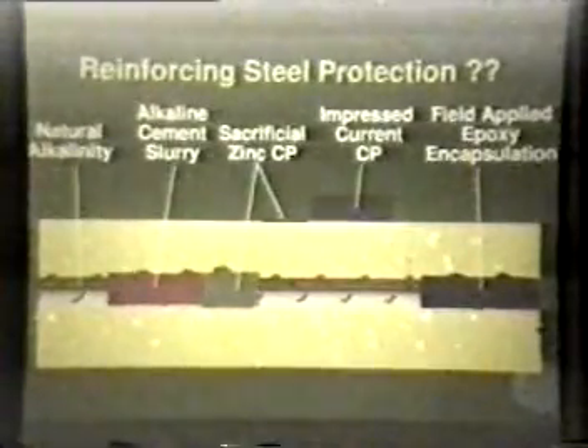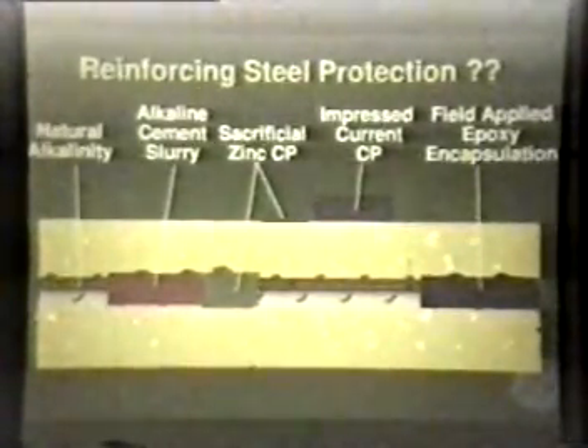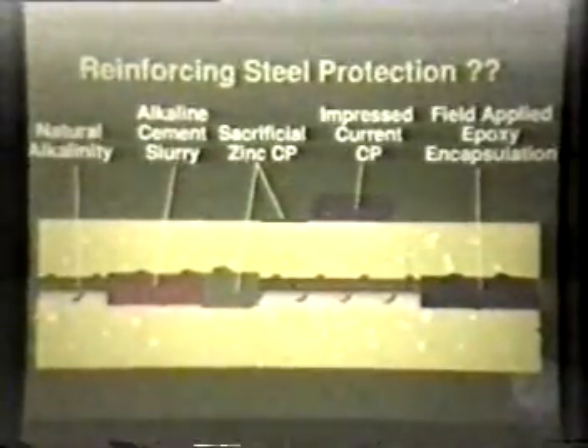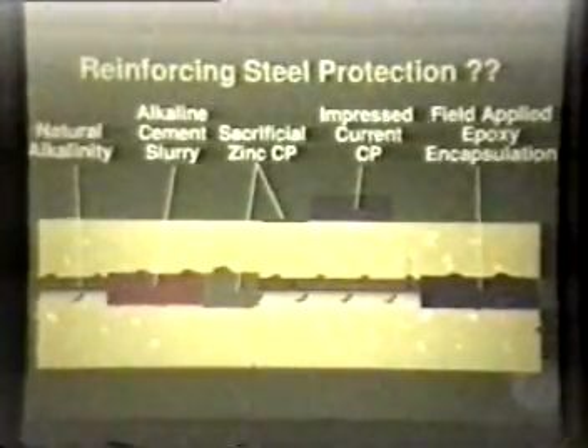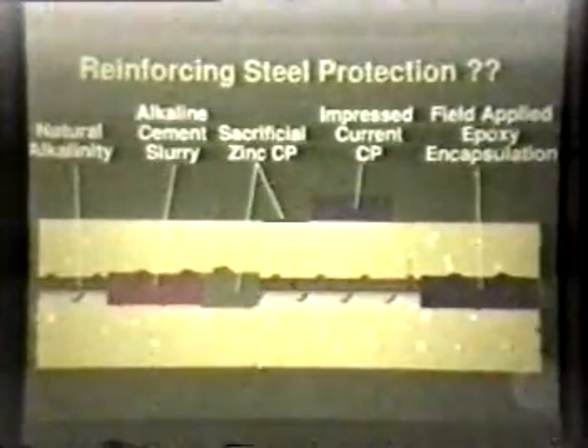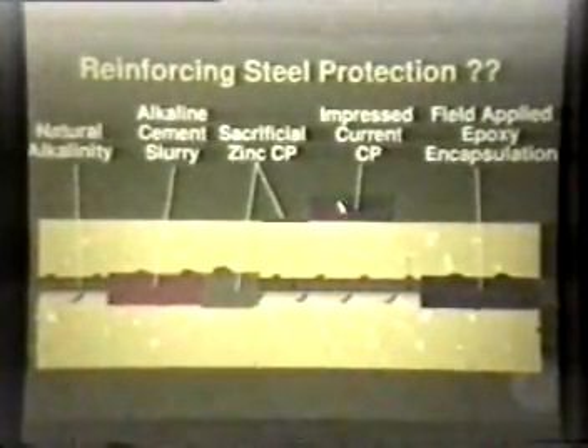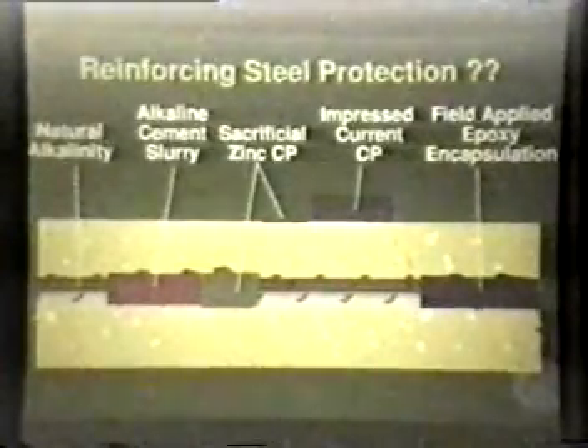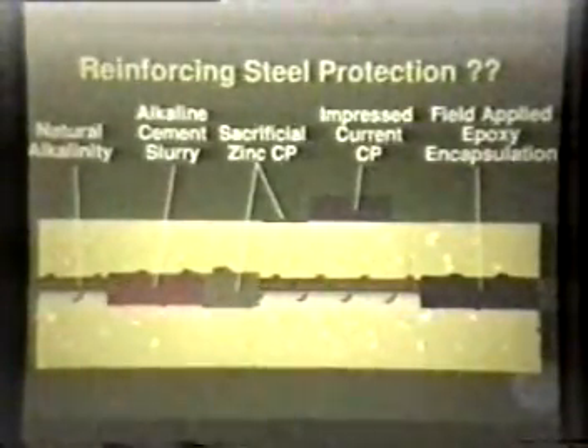In general, what I see is the epoxy coating systems have fallen out of vogue for repair and have led to different specialty coating systems that are based upon either the alkalinity protection. The alkalinity of concrete is a natural protection. It has a high pH, and that high pH is what protects the concrete. It causes passivation of the reinforcing steel, and it really protects the bar. So some of these systems are basically the alkalinity, similar to concrete, in a coating form that's applied to the bar. There's sacrificial zinc systems that are really passive cathodic protection systems that have been around a long time. And of course, we'll be talking a little bit later about the impressed current cathodic protection systems. What I just talked about earlier was the epoxy coated, the field applied epoxy coating system.